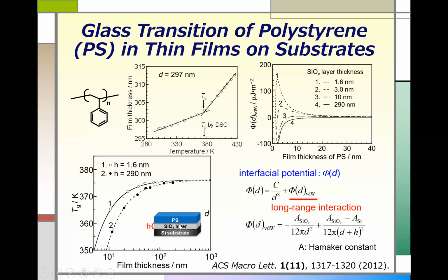All right, nothing special. Then we prepared a thin film of this polystyrene on this silicon wafer using a spin coating technique. We first made a solution of polystyrene in toluene, and then the substrate is rotated, we put a droplet of polymer solution on it, and then dry it. Then eventually, you can prepare thin films. And this is how we are able to determine the glass transition temperature of this thin film, right? We can measure the thickness by using an ellipsometer or X-ray reflectivity.